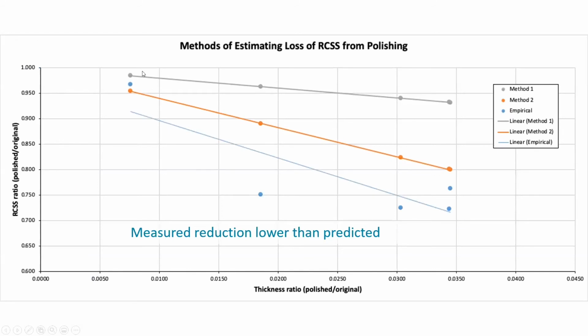So for this first one, this gray one that we talked about, we anticipated that if we just use the graph that we had measured, then we could estimate or extrapolate where we think the RCSS would go. And what we found there is that, as we anticipated, that does not in any way address the rebalancing of the stresses locally through that thickness, because if we still have the full RCSS on one side, it's got to rebalance. So we attempted a little bit of algebraic magic and see if we could come up with another model that tried to address that. And that's this orange line.